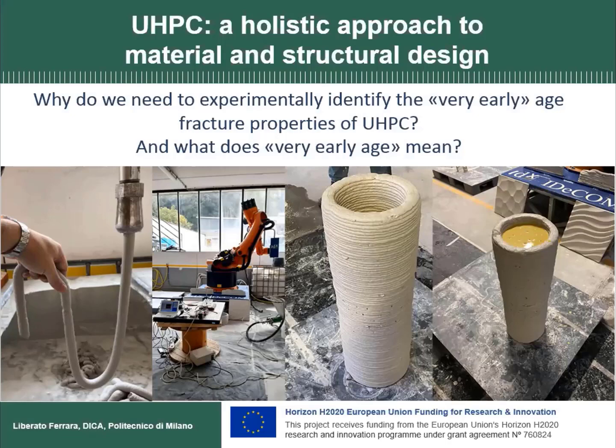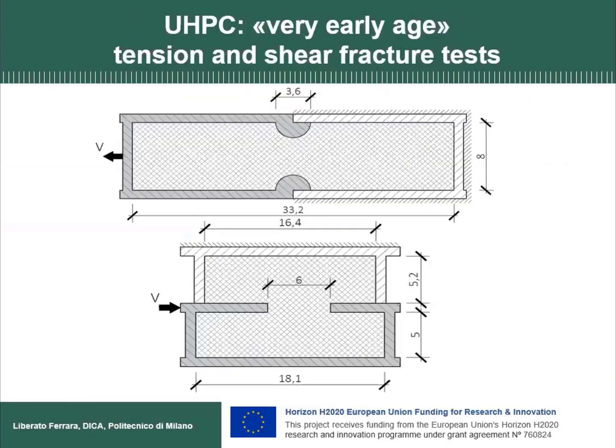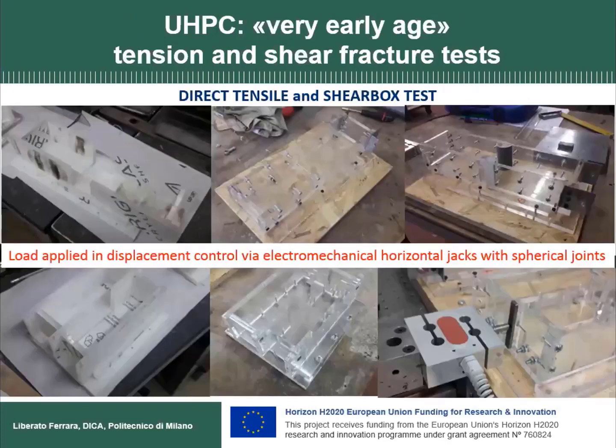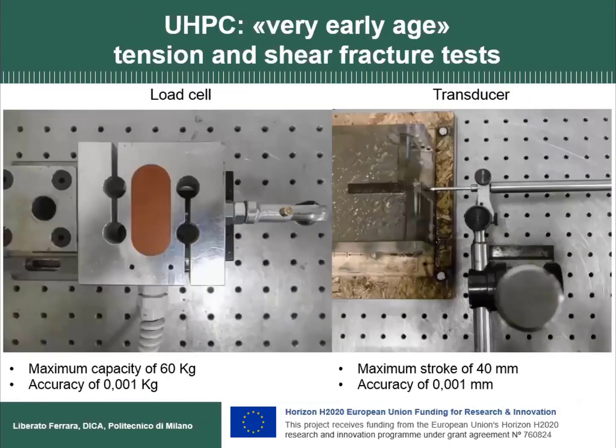So what does very early age mean? Here we focused on the properties up to 2-3 hours after the end of the mixing. We developed these tensile and shear fracture specimens. You can see the measures are in centimeters, so they are quite compact. We developed them like that because we also wanted to make this setup portable to different sites. And these are the molds. We equipped them with a load cell able to apply the load in displacement control. We need very sensitive equipment, so we use a load cell with a maximum capacity of 60 kilograms and an accuracy of 1 gram.